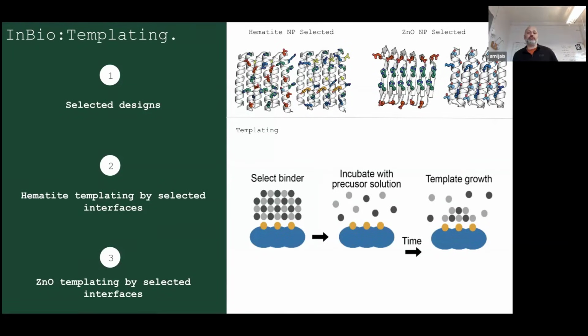We had 2 designs that seemed to bind hematite very well. They all had coordinating residues, histidine and tyrosine and so on. We also found things that seem to bind very strongly to zinc oxide. On the right-hand side, the left one of the right are beta-solenoids with a lot of histidines and glutamates, and on the right side you see another protein, but this one only has threonine. We're quite curious whether the mechanism there has to do with water ordering, because we know that threonines organize water through a clathrate mechanism.